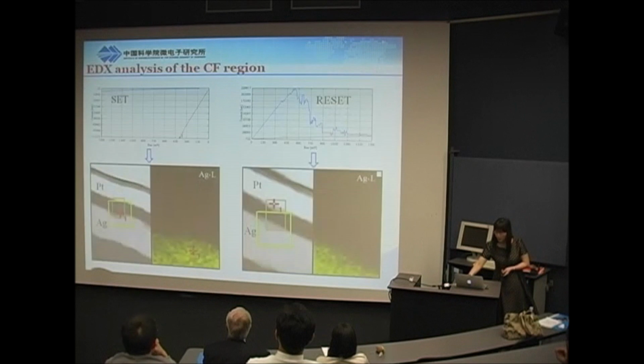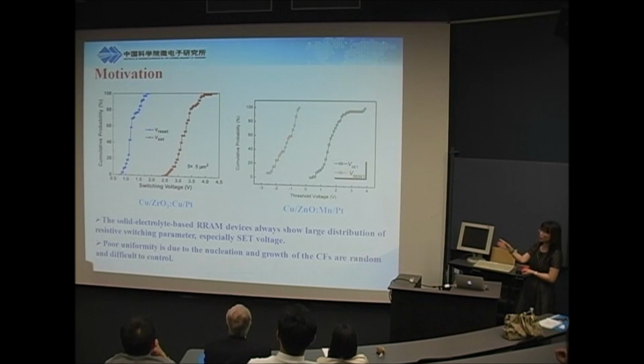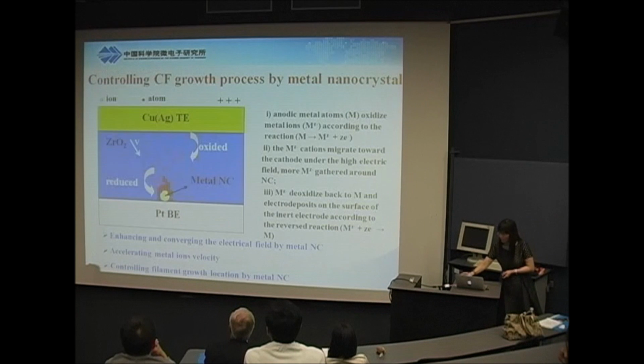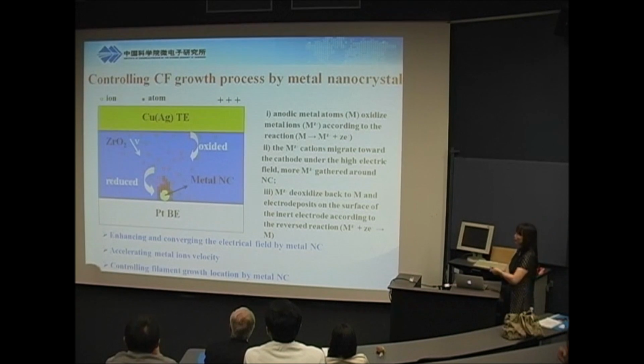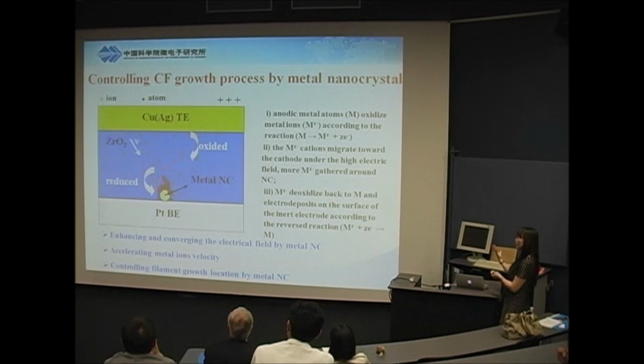You cannot fix it. So if you would like to fix this distribution, you should try a way to control the filament forming process. So we tried a very simple way. If we add some nanocrystals in the bottom electrode, we can see what will happen. So here is a nanocrystal. That means there is a strong electric field on the tip of this area. We imagine we can enhance the electric field around this area, especially at the tip, and also accelerate the moving speed of the metal ions. That means we can control the filament forming around this area.